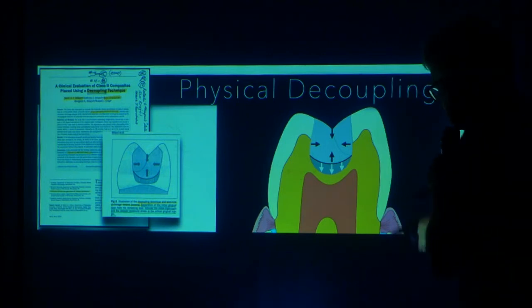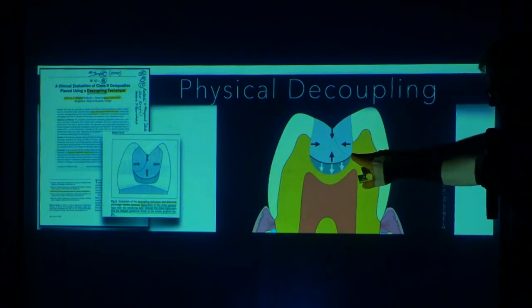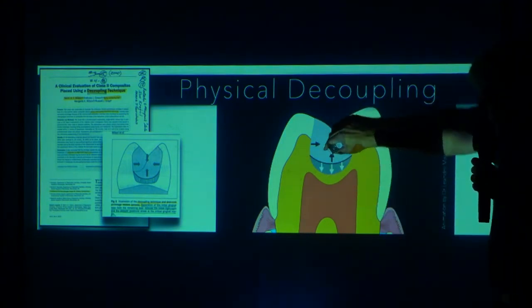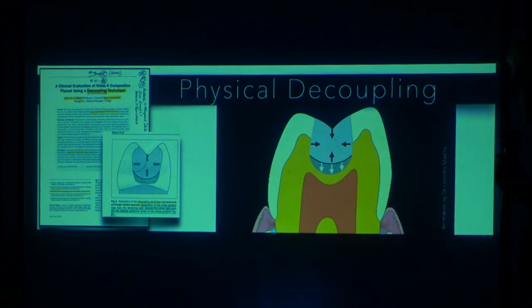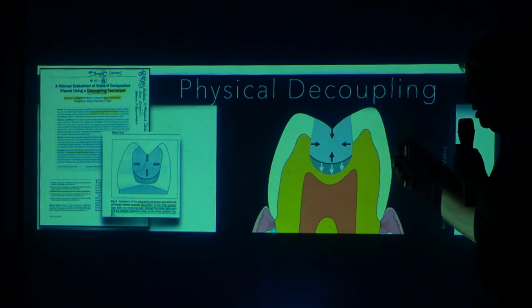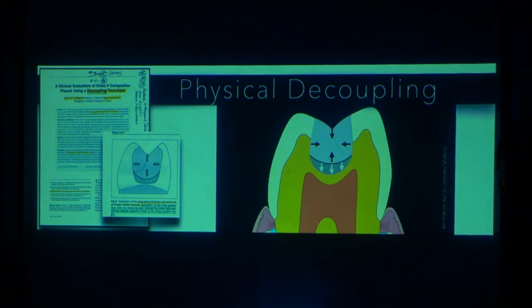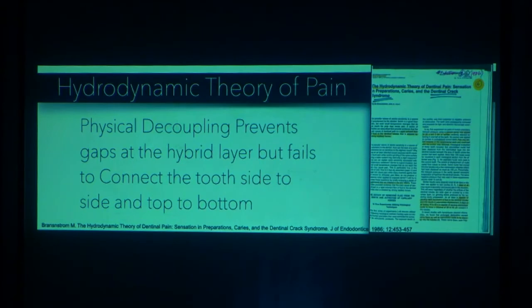And that was because the composite was moving towards the tooth in the most critical area. This massive shrinkage was not affecting this lower layer. But the downside is, what if you're missing a wall? Then all of a sudden, you don't have a connection top to bottom, and so the top of the restoration moves in a different direction than the bottom, so it was limited to class one restorations. Brannstrom, when he gave us the hydrodynamic theory of pain that now we call the hydrodynamic source of pain, said that physical decoupling prevents these gaps at the hybrid layer, but it fails to connect the tooth side to side, top to bottom.